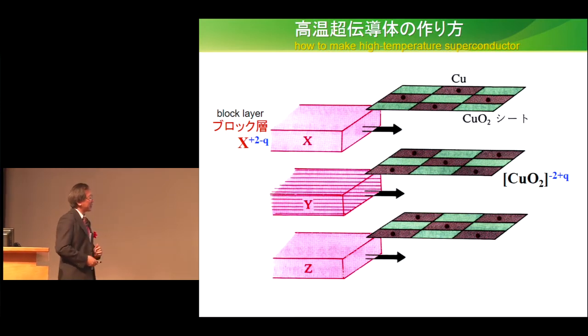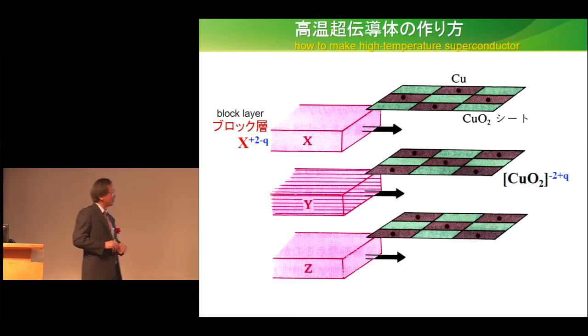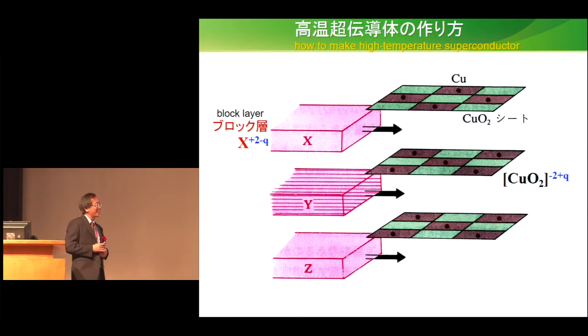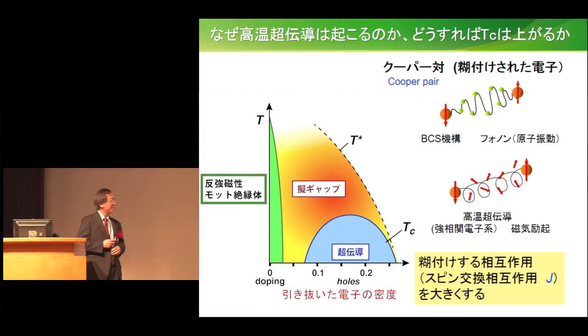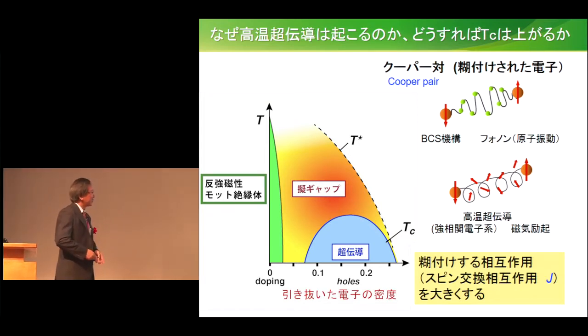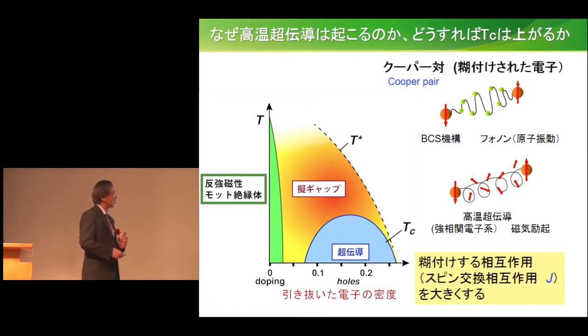This is a copper oxide sheet. This is about 1 nanometer in distance. And we insert the blocking layers of ions, and the total charge can be controlled, and then we can add or withdraw electrons from the sheet. When the electron crystal, where the electrons are immobile, is operated on by withdrawing or adding electrons, we are able to induce electron liquid, which is the state of high temperature superconductivity. This shows the number of holes inserted as density, and this shows the magnetism in the state of Mott insulator. But when electron density changes at one time under a certain temperature, superconductivity can be realized.